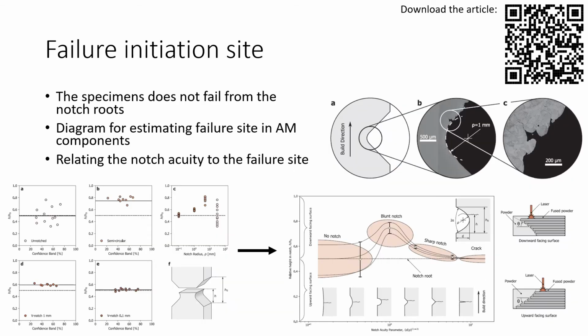And further, we capture the failure initiation sites for the specimens, and what we saw was that unnotched specimens have a large scatter, while the semicircular specimens are failing from the downskin region. So is the V-notch specimens with 1 millimeter radius, while the V-notch specimen with the sharp notch have failure from the center.